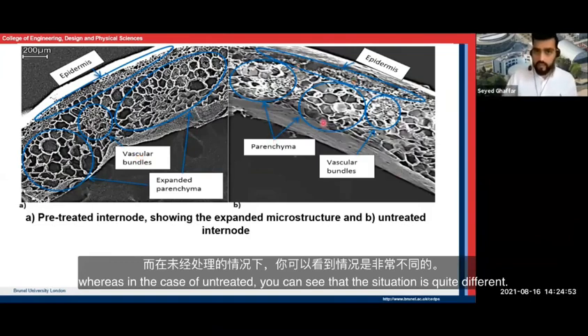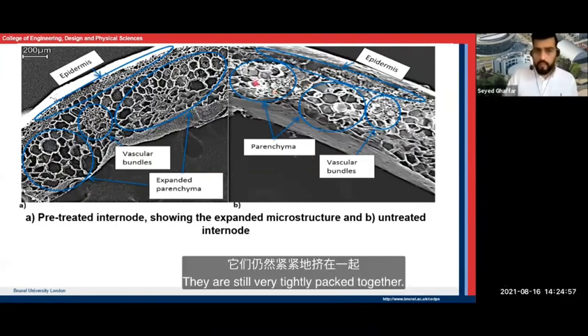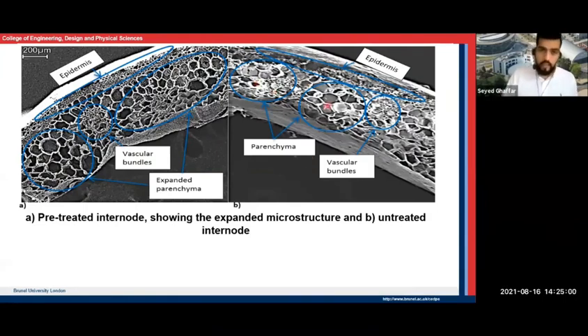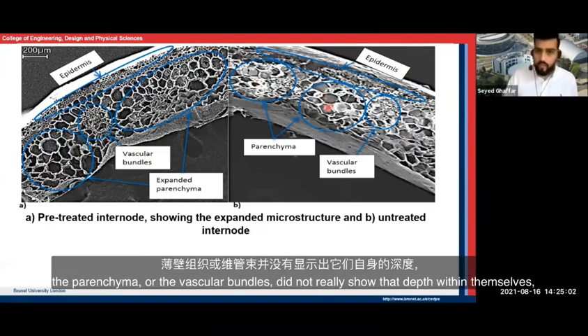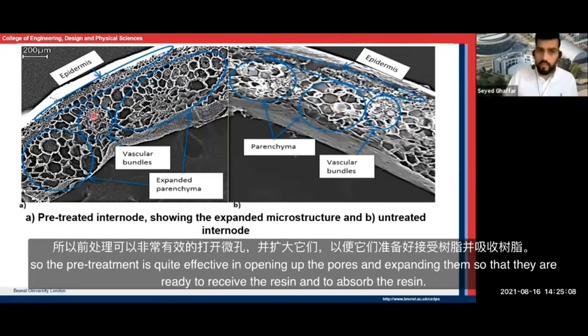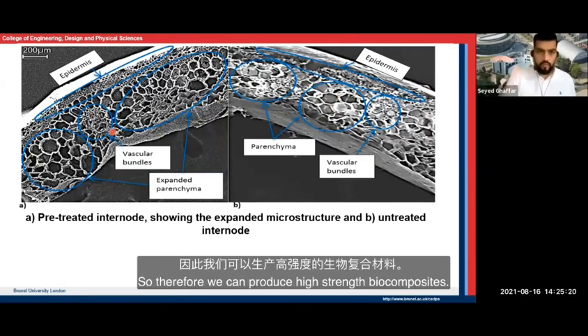Whereas in the case of untreated, you can see that the situation is quite different. They are still very tightly packed together. The parenchyma or the vascular bundles do not really show that depth within themselves. So the pre-treatment is quite effective in opening up the pores and expanding them so that they are ready to receive the resin and to absorb the resin. So therefore we can produce high strength biocomposites.